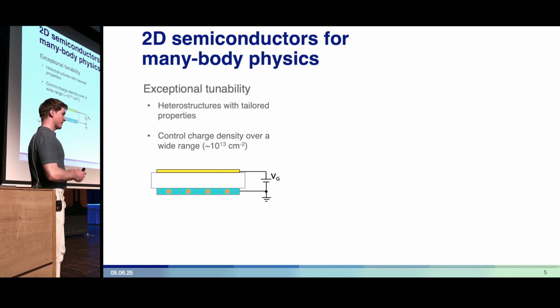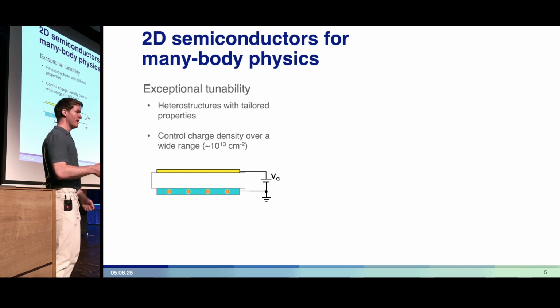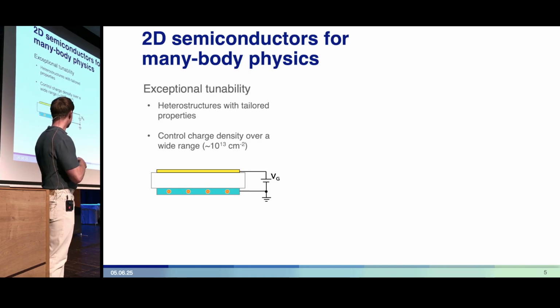So if I put together these different aspects, I can actually take a 2D material and stack it into a structure such as this, and I get a new device which has a wide range of tunability. This is a simple field effect device where I have a monolayer semiconductor, an insulating barrier, and a layer of conductor on top. These are capacitively coupled to each other, and I apply a voltage between the two of them.